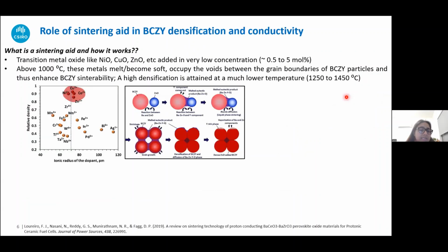So that's where the role of sintering aids comes in, to promote densification at lower temperature. So let's first look at what a sintering aid is. It's basically a transition metal oxide, like nickel oxide, copper oxide, zinc oxide, which is added in a very low concentration to the mother material, which is BCZY. So as you can see in this plot over here, why are these materials chosen? Because they have ionic radii very similar to that of zirconium, and that's one of the reasons why they show favorable results when we are doping. This is not really, I would say, doping, but more like an external aid, which, above 1000 degrees, these oxides melt or become soft, and then they occupy the void space between the grain boundaries, and then it assists the densification together.